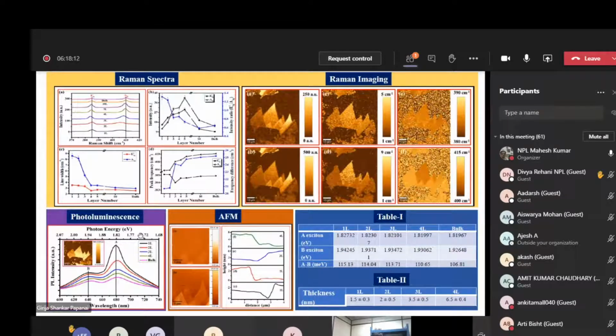Further, the PL mapping and PL spectra have been performed for the number of layer determination, and there are two excitons found here at 637 and 679 nanometer, and the corresponding energy values have been given here. The valence band is splitting between the two, the A exciton and B exciton, as shown in table 1. If you see table 1, there is a monotonic decrease when we go from one layer to bulk. So this value of the valence band splitting can be easily used to determine the number of layers, and further we